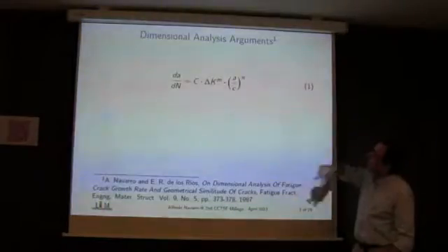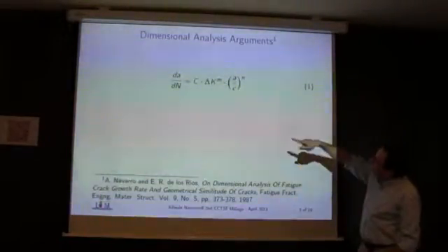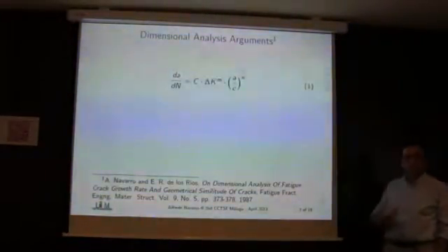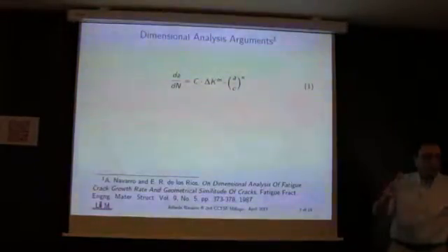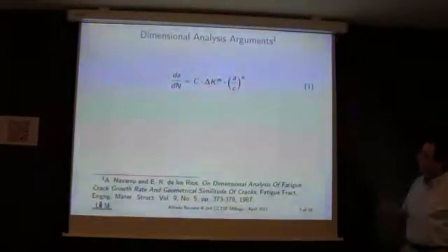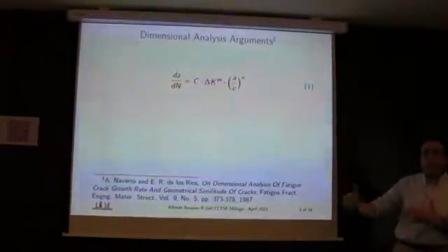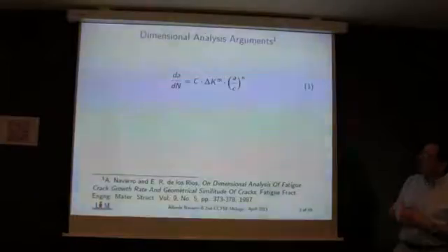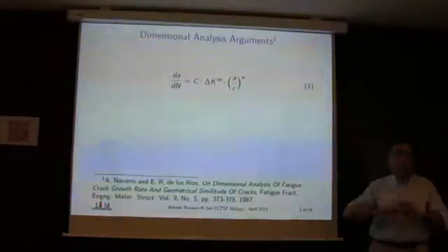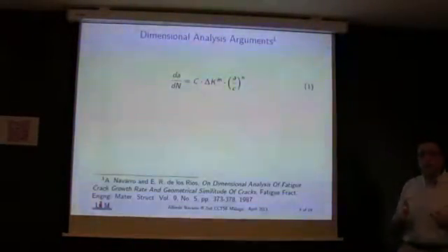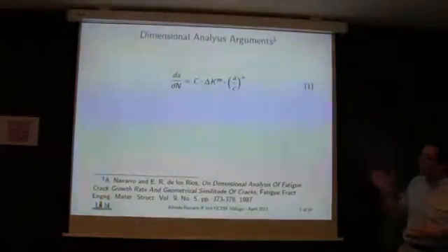It's a constant, delta K, and then you also have the influence of the only two dimensions that we're seeing in the problem, which are the crack length itself and a new length which also encompasses the plastic zone. If this is the growth of a crack in an infinite medium, there are only two lengths there, so it makes sense that they should appear.